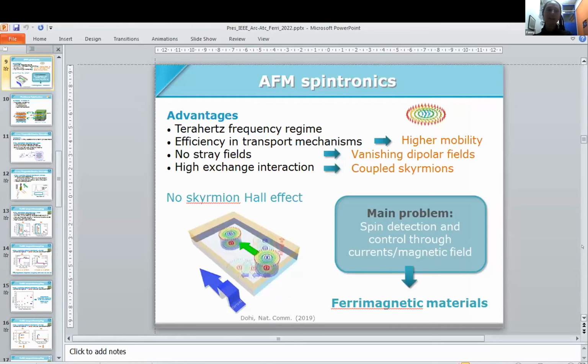And finally, in antiferromagnets, you have a high exchange interaction, and this will allow you to have coupled skyrmions. When we are talking about coupled skyrmions, it is one skyrmion in one lattice of the antiferromagnetic material, and one skyrmion of the other lattice, and they will be coupled together. Why this is fundamental is to be able to get rid of this skyrmion Hall effect. If you have one skyrmion of one lattice, it has one chirality. When you apply a spin current, normally it will go in one direction. If you have two coupled skyrmions, actually they will compensate the motion, the trajectory of the motion, and basically you will have one coupled entity that will go straight.